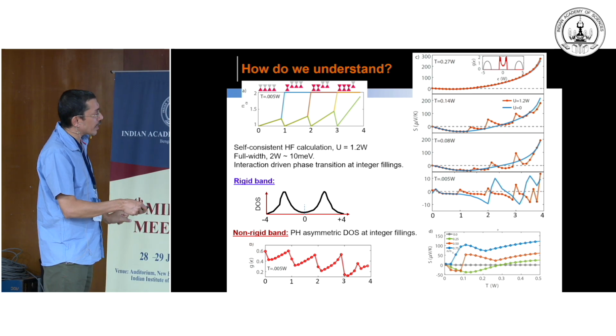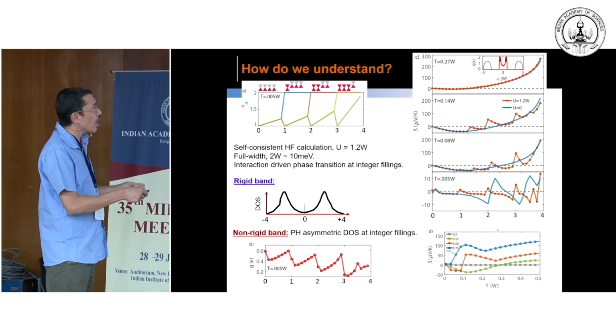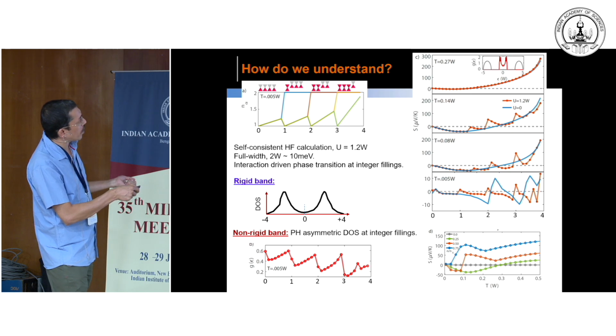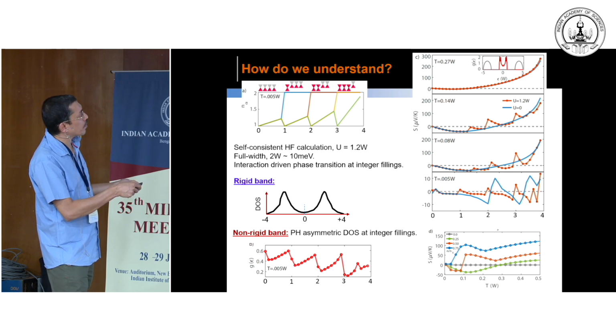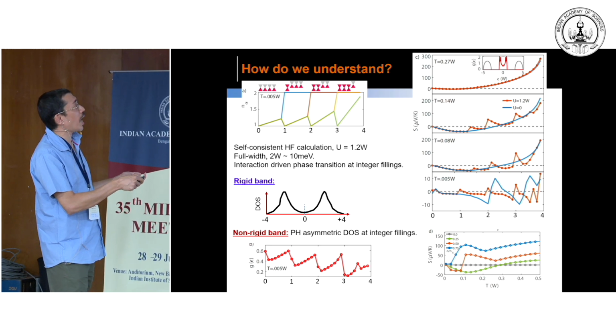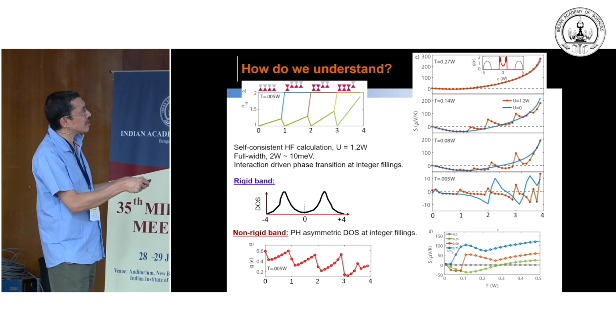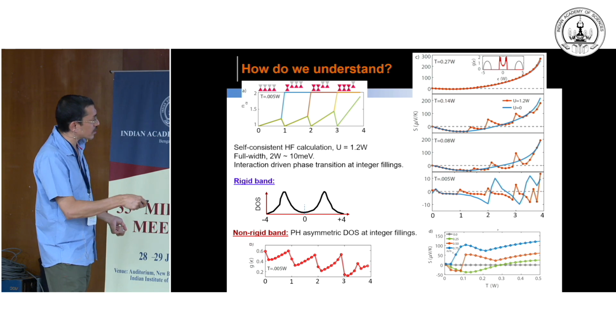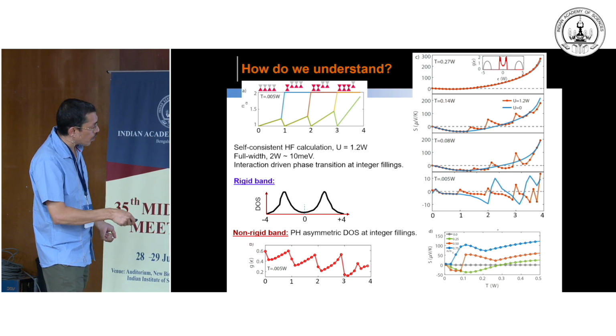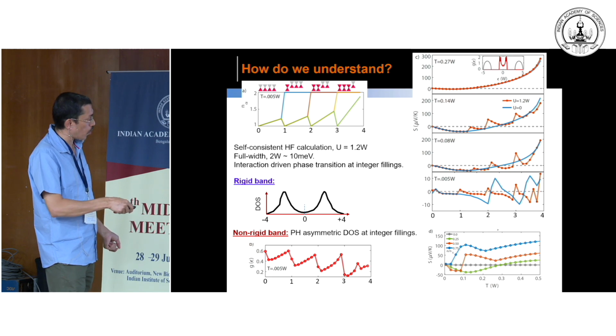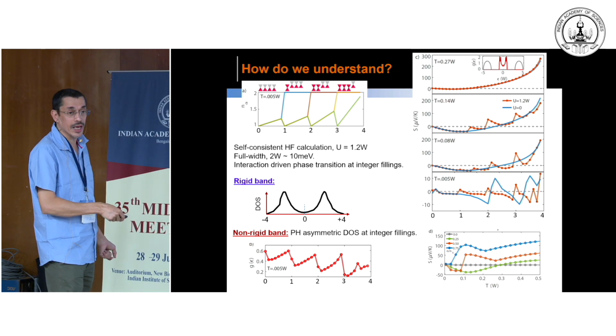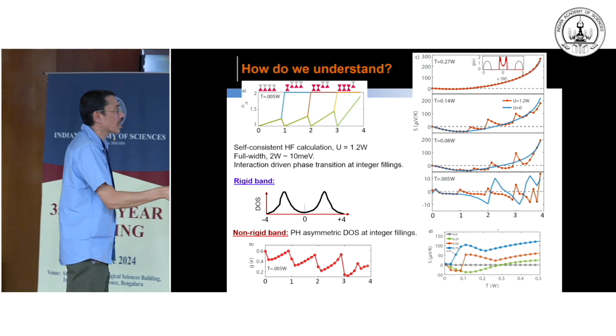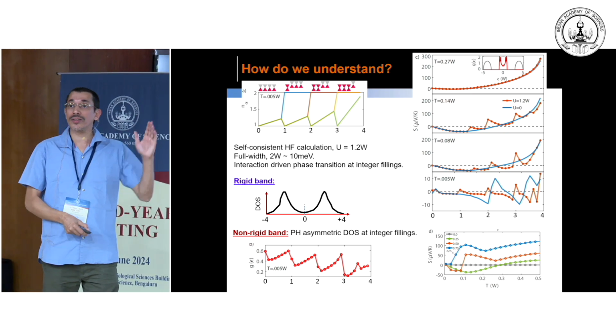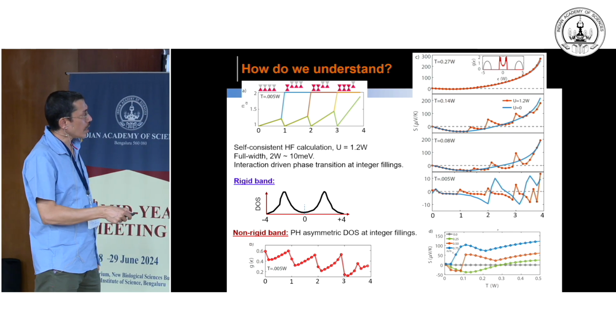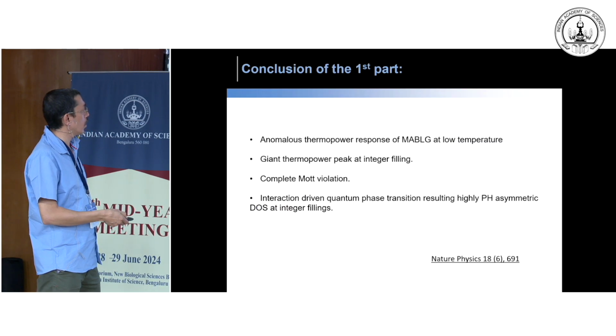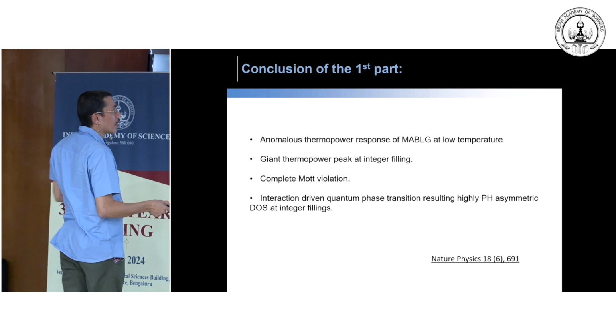So the way we understood it, that's the last slide probably, from mean field calculation, is that the rigid band picture of a flat band I was talking about is not true. Because of the interaction, the four flavors which are supposed to fill equally behave differently: one flavor gets completely filled and the other flavors are completely empty, and this happens at integer filling because of the interaction. As a result, instead of a rigid band, you get a density of states which is modulating and has a large particle-hole asymmetry, and that is captured in our theoretical calculations, which can explain the large thermopower peaks at integer filling.